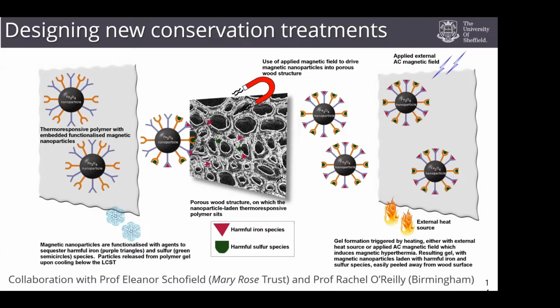And I apply this to the Mary Rose, with the particles inside a polymer gel, a bit like a face mask. And we then change temperature by just a degree or two, and this gel turns into a liquid. And in that liquid state, it releases these particles that can enter the ship, spend some time incubated within the wood, and try and latch on a bit like a Pac-Man to these free iron ions. Then we can use a magnetic field to draw the particles out. And if we change the temperature back again, we can turn that liquid back into a gel and just peel it off the ship.